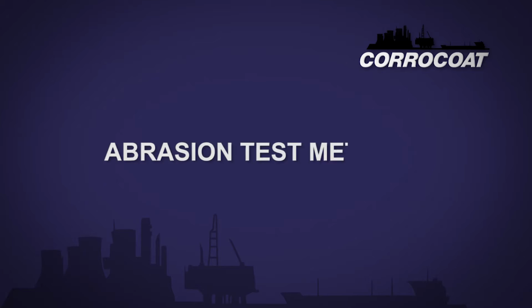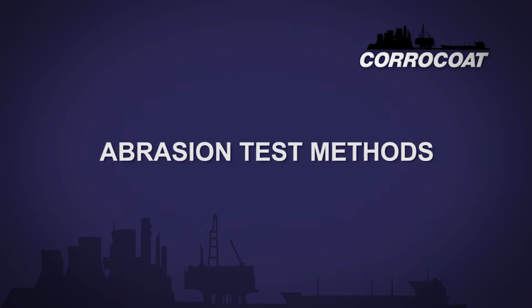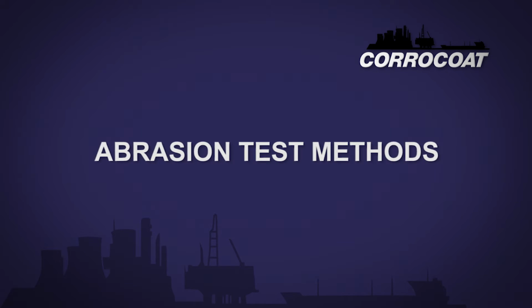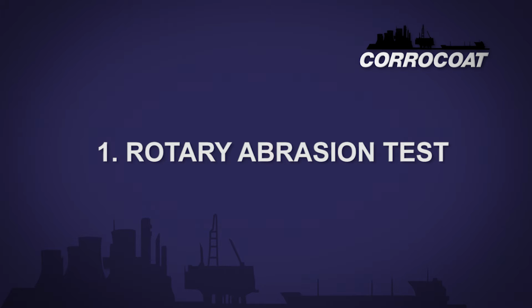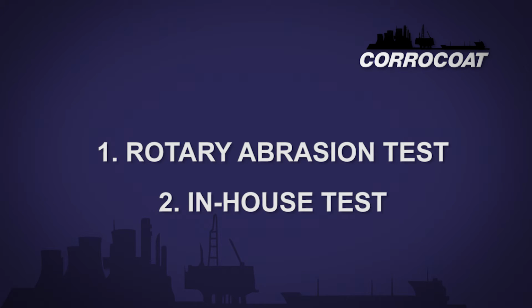Because of the foregoing, testing using a standard test method is by no means certain to be representative of that material's performance in a particular environment. In fact, testing using a standard test method is fraught with difficulty and can often give spurious results. We are concerned primarily with linings, coatings, and paints, and use two particular test methods. The first is the rotary abrasion tester. The second is an in-house test devised to overcome some of the issues with the first. Whilst by no means being a problem-free solution, it is effective.